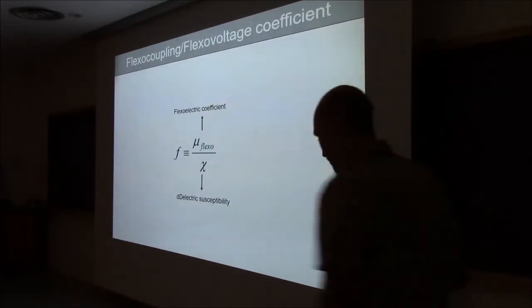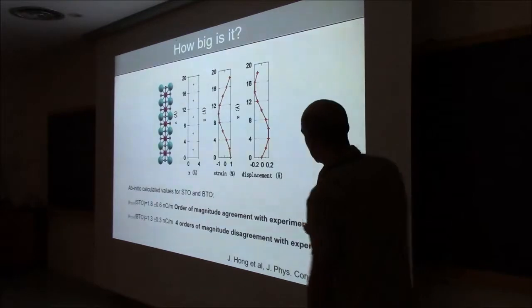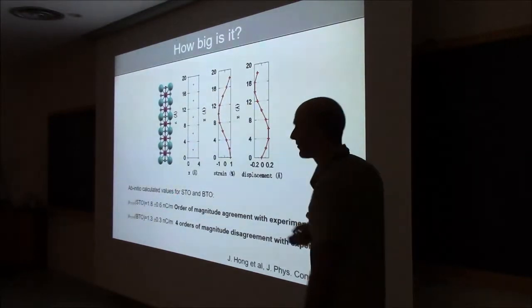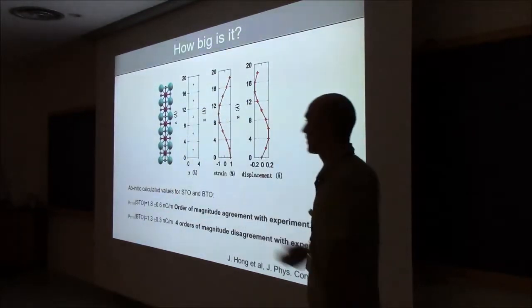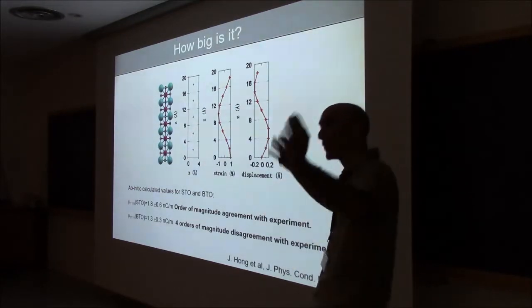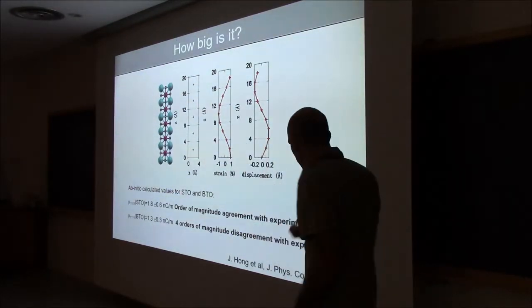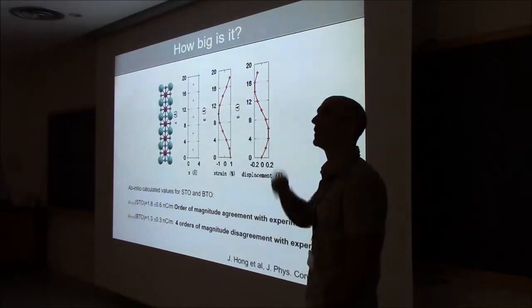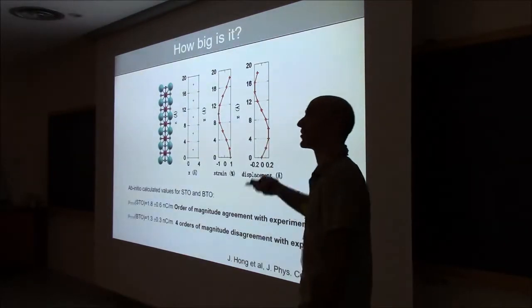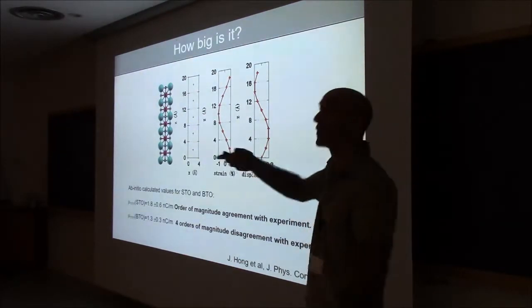Okay, and the first thing that we thought is, okay, DFT is usually calculated at 0 Kelvin. Everything is perfect, there's no defects, and everything is at 0 Kelvin. But we know that flexoelectricity is proportional to dielectric constant, and dielectric constant changes with temperature.